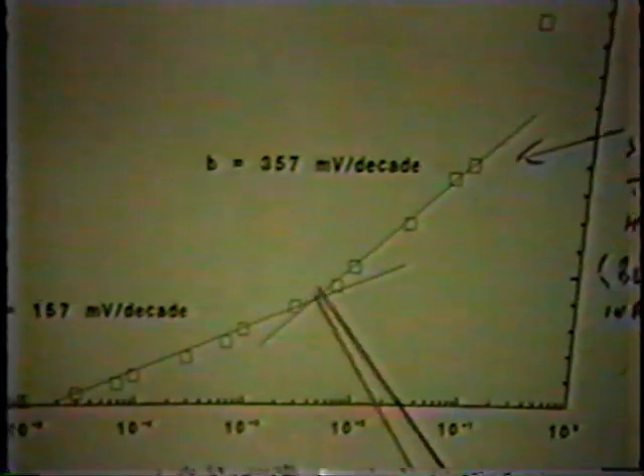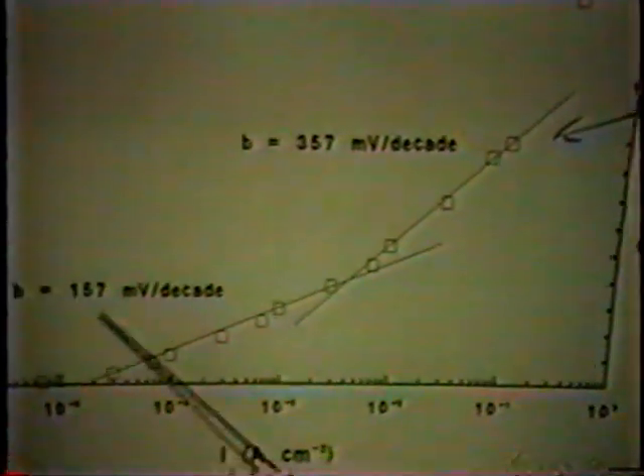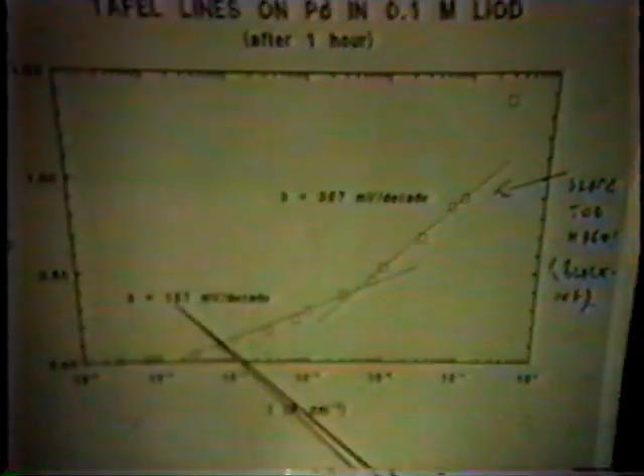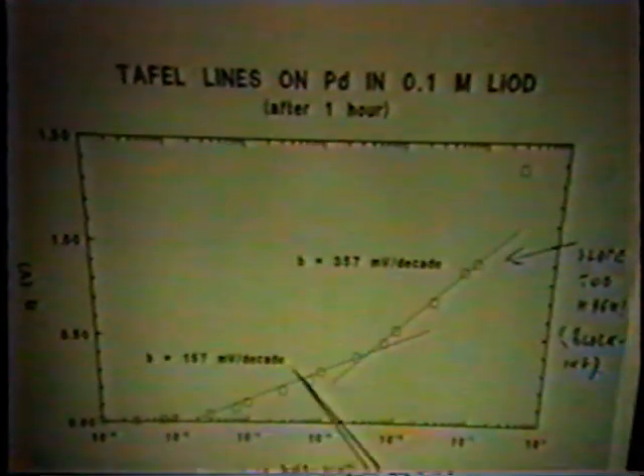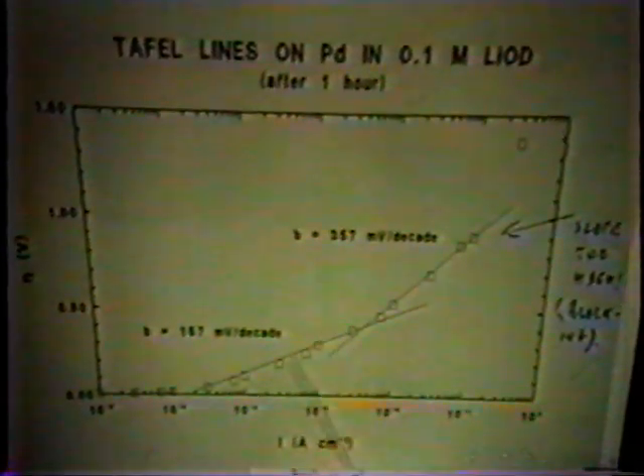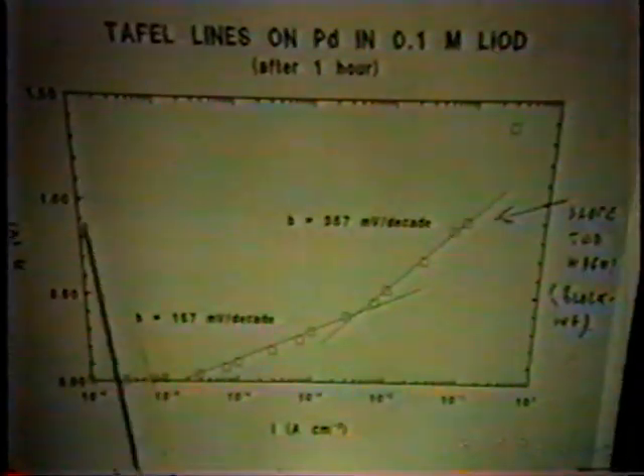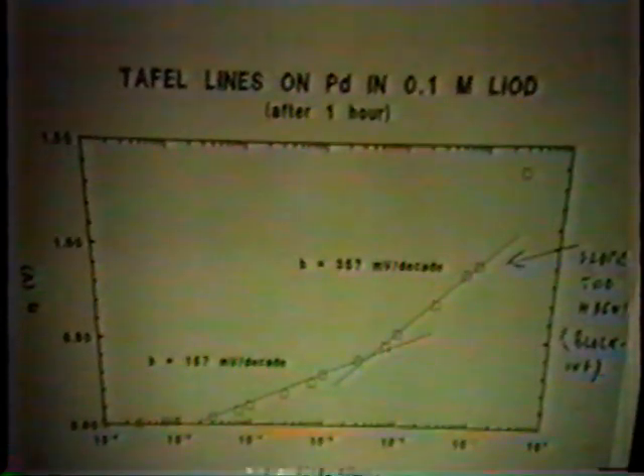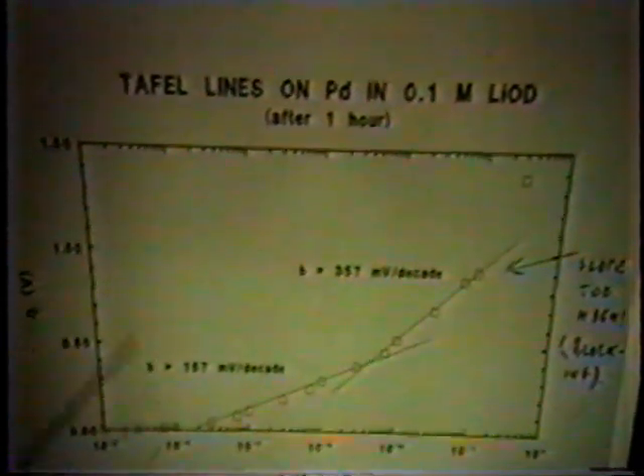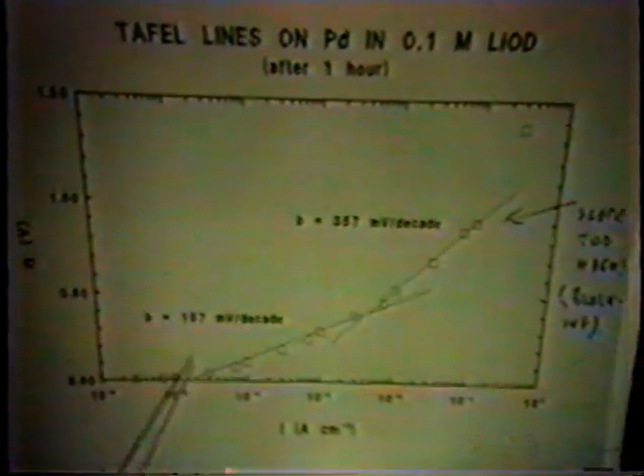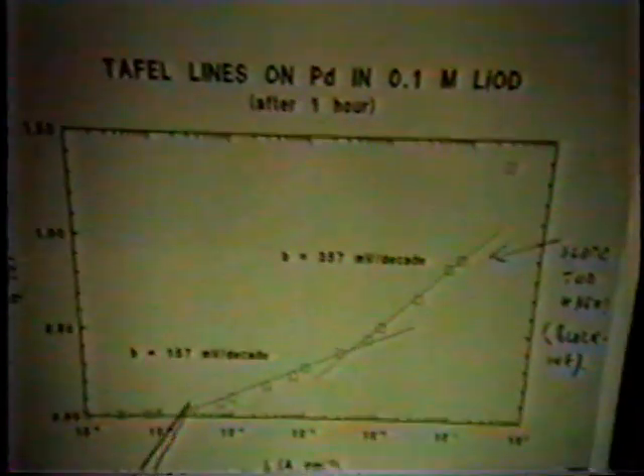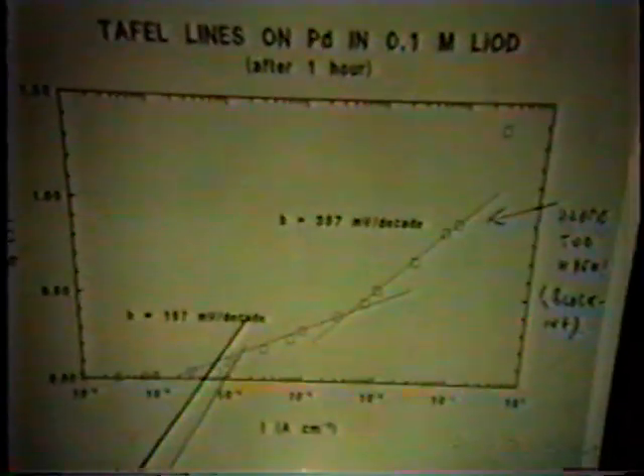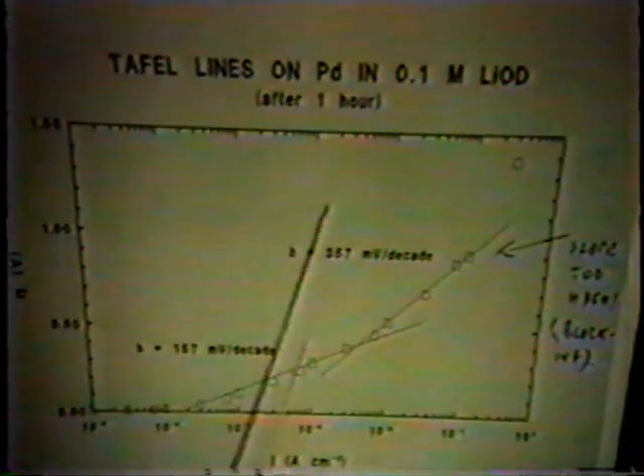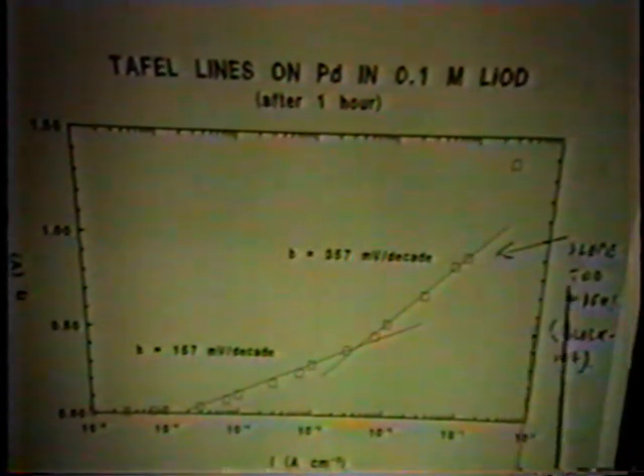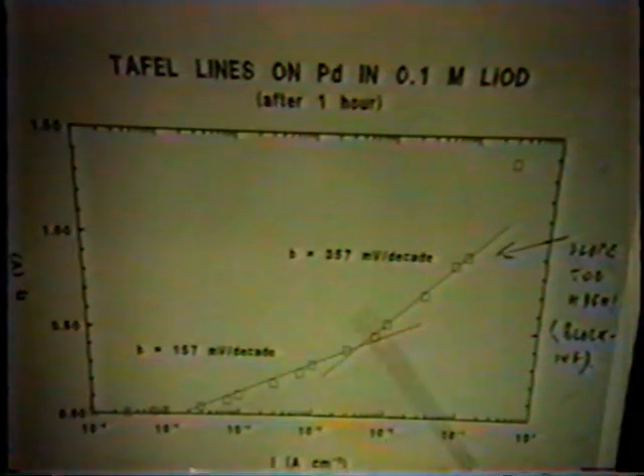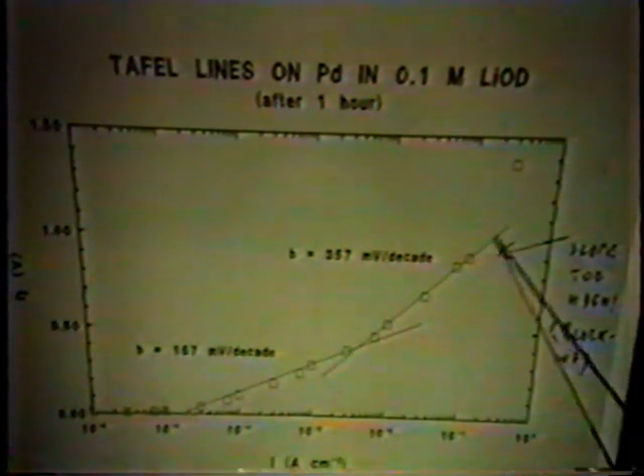Now, the theory of electrochemistry, electrokinetics, says that this kind of Tafel slope, this B, this gradient of log I, is quite reasonable. It's a bit high. In theory, it says it should be 127 at this temperature, and it's 157, but such deviations are not unusual, and we should count it as agreeing with the theory that I suggested earlier on solubility. But to explain 357 at all, you can't do it. 357 is far too high.